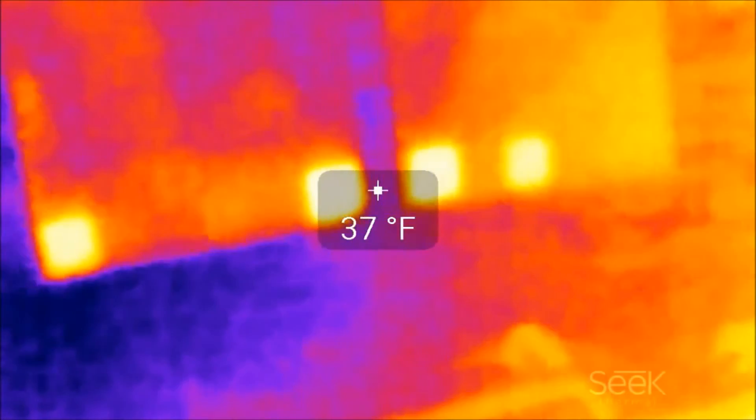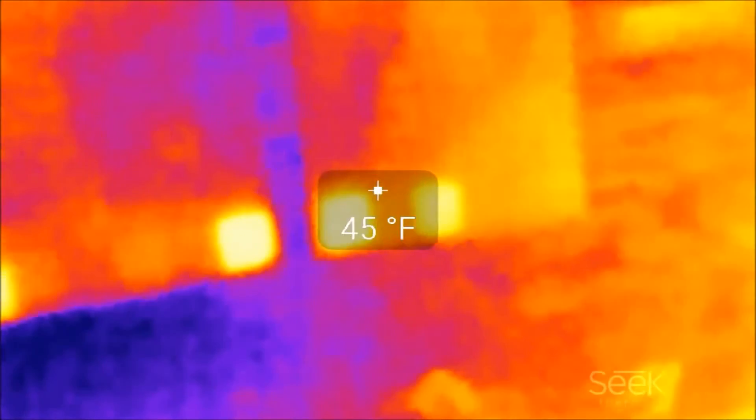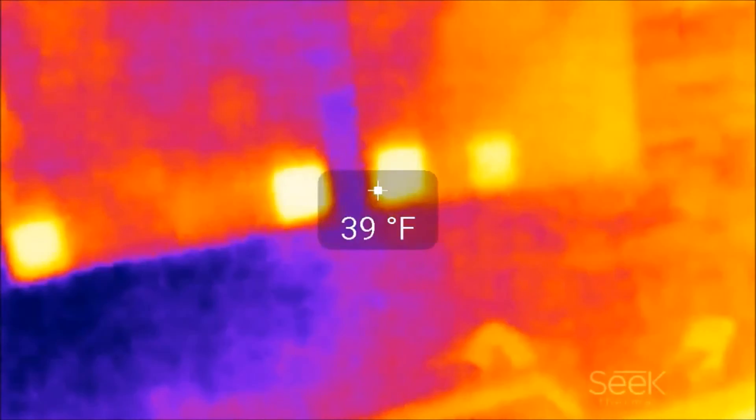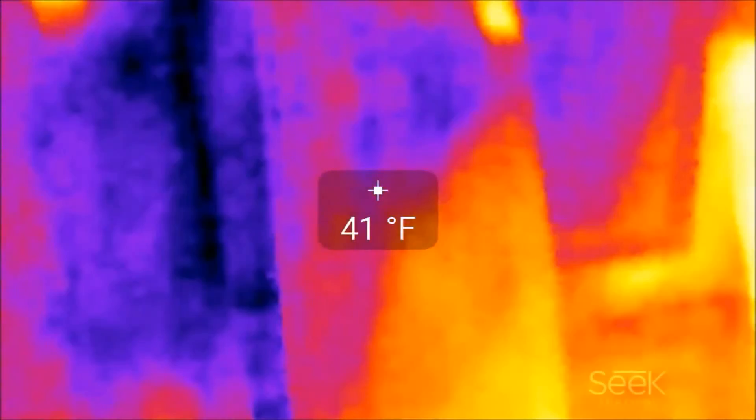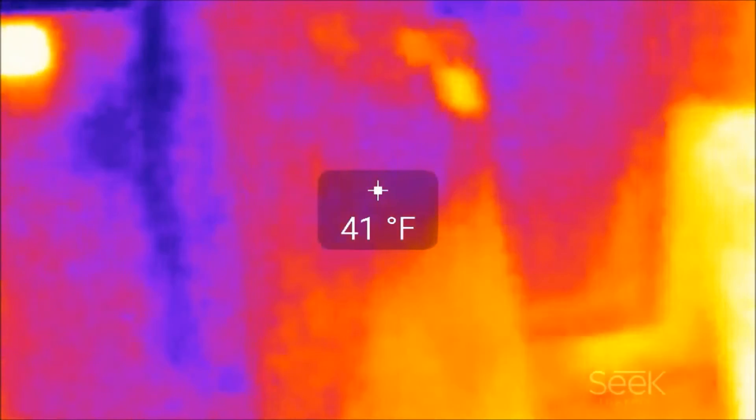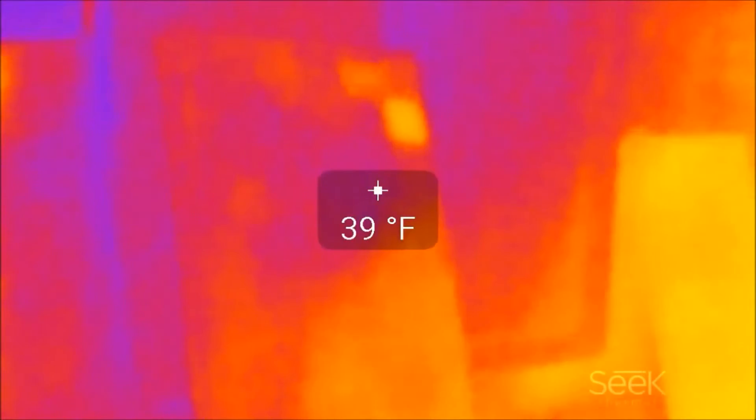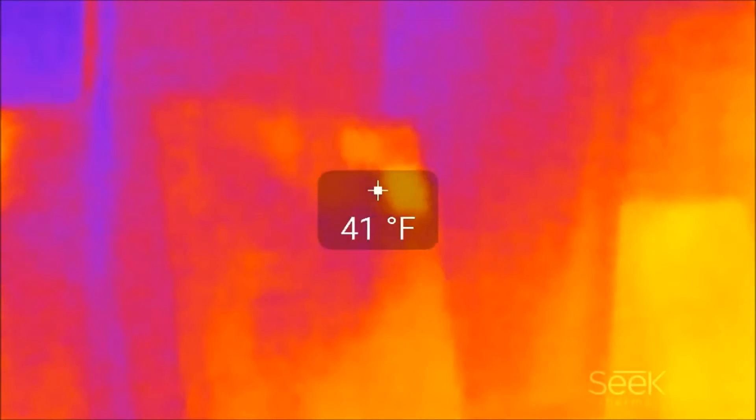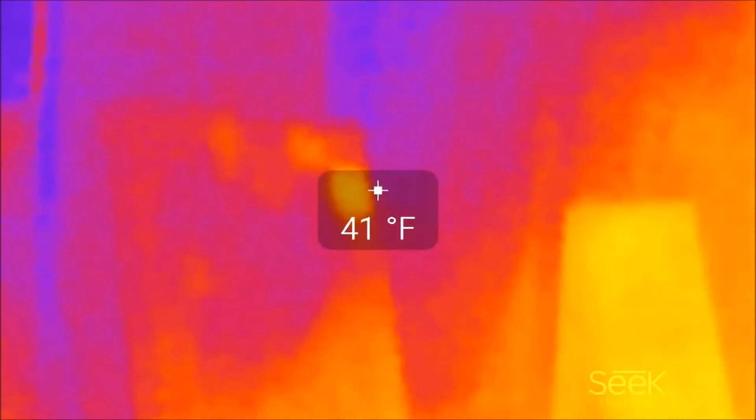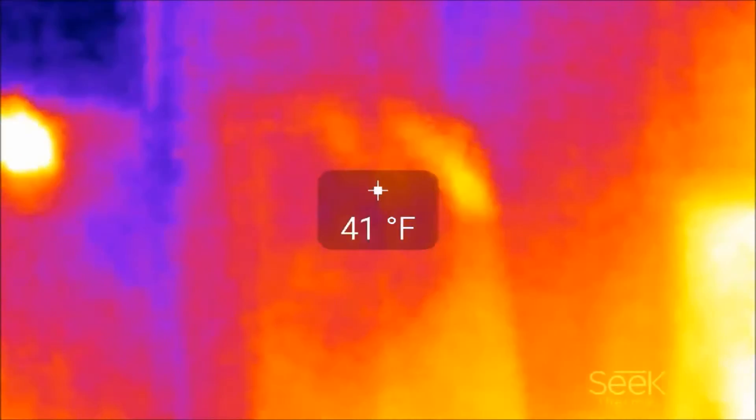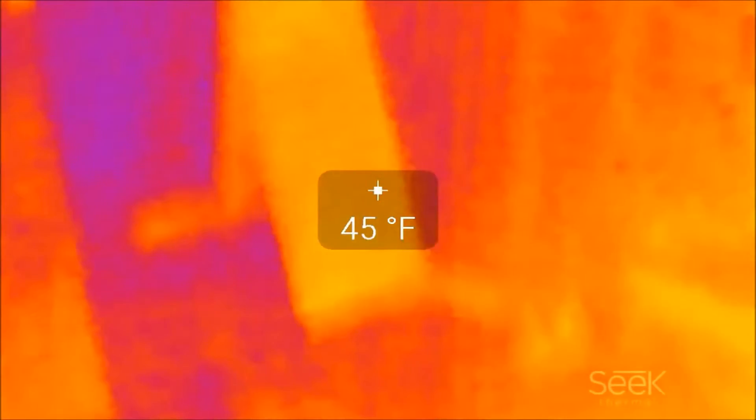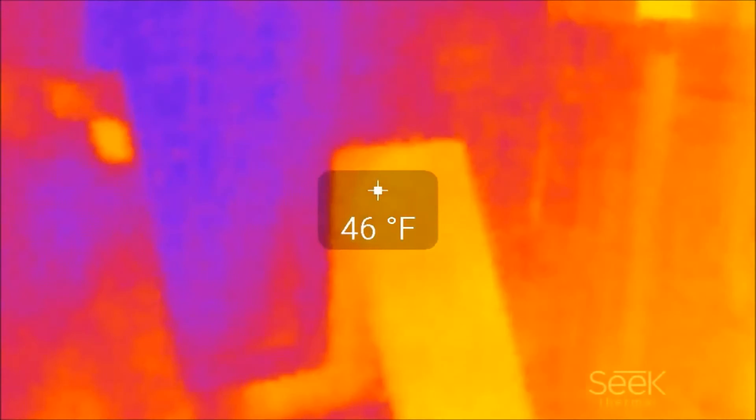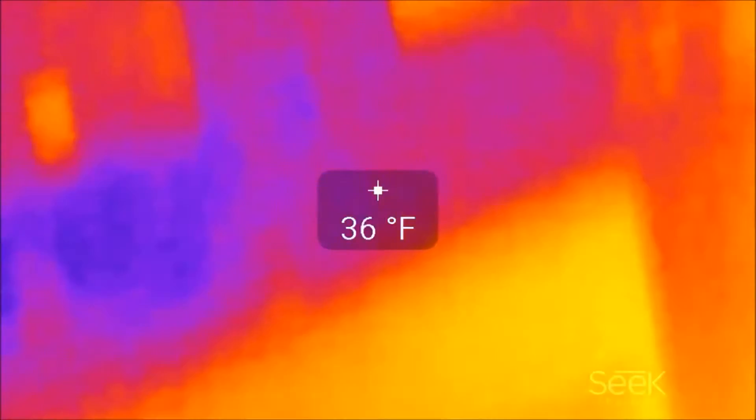That's pretty significant. The power is going through the solar cells and when it reaches those damaged cells, the power is being dispersed as heat and it never makes it to the charge controller. That's the amorphous panel and that looks pretty normal.